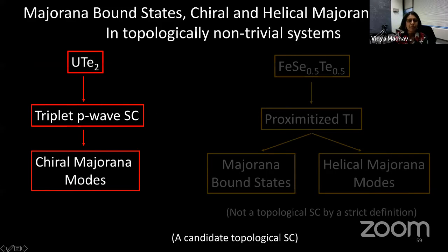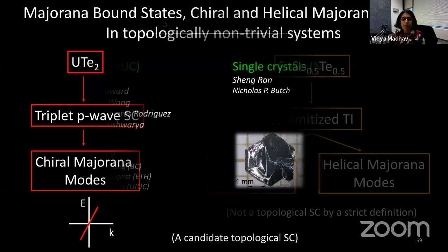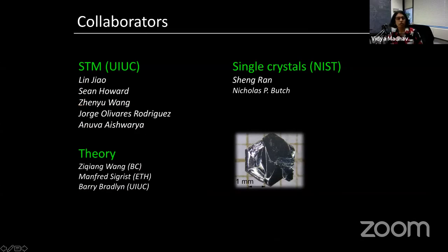I wanted to mention this because it's exciting. It's a different system. We think it might be a triplet, chiral triplet p-wave superconductor, which in theory should have chiral Majorana modes, unlike the proximitized system, which has helical. And by chiral, you immediately see only one branch of these propagating Majorana states at the edges, which means automatically that time reversal symmetry should be broken below Tc in this system. This work was done in collaboration with Sheng Ran and Nick Butch at NIST, and they gave us these very nice single crystals. And these are the other people involved in this work.